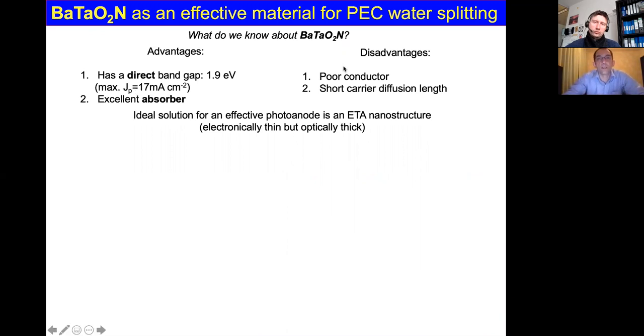So there are advantages and disadvantages. In the case of advantages, the material has a direct band gap, which is 1.9 electron volt, and this material is an excellent absorber. However, this material is a poor conductor and has a short carrier diffusion length. It's similar to the bismuth vanadate.